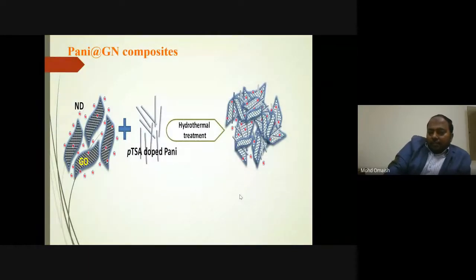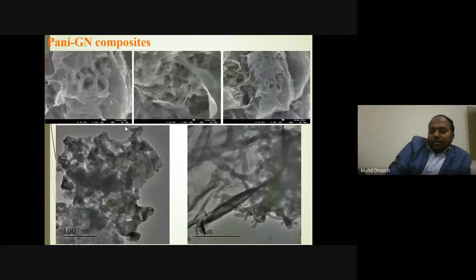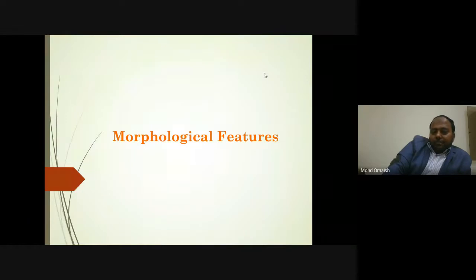Similarly, a lot of other composites have been prepared, like polyaniline graphene oxide doped with carbon-based materials. This is by hydrothermal treatment, and here we can see a mixture of polyaniline nanofibers as well as sheets of graphene oxide or graphene. This is by SEM, and this is the TEM image.